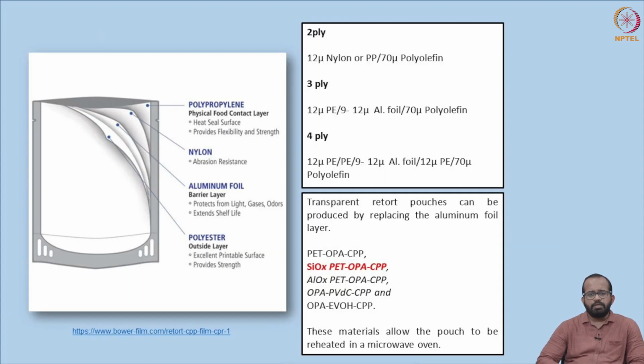In a normal retort pouch, there are different layers: 2-ply, 3-ply, 4-ply layers. Normally, there will be an inner polypropylene layer, optionally a nylon layer, an aluminum foil, and an external polyester layer. So these are the normal layers of a standard retort pouch. In the case of 2-ply, there may be a 12 micron nylon or polypropylene and 70 micron polyolefin. In 3-ply, it is 12 micron polyethylene, 9 to 12 micron aluminum foil, and 70 micron polyolefin. And in the case of 4-ply, it is 12 micron polyethylene, 9 to 12 micron aluminum foil, then 12 micron polyethylene, and around 70 microns polyolefin. So this depends upon whether it's a 2-ply, 3-ply, or 4-ply. Different kinds of materials will be added.